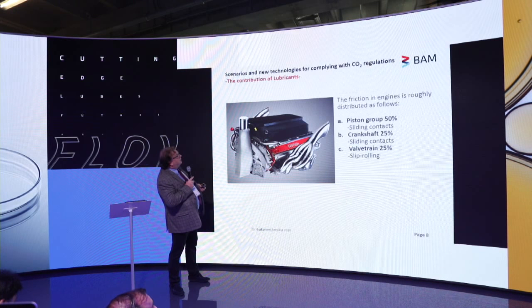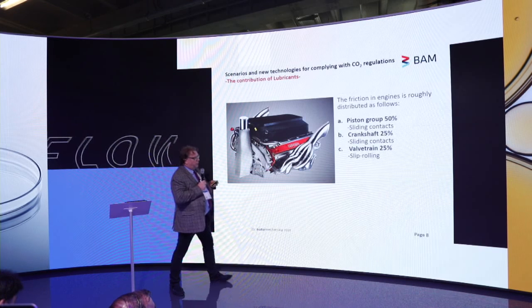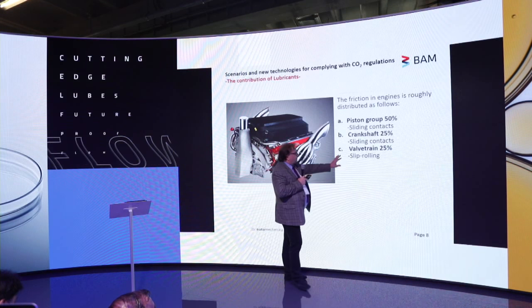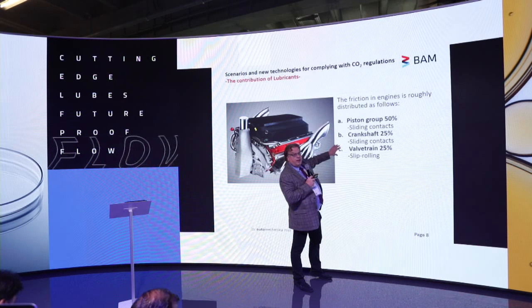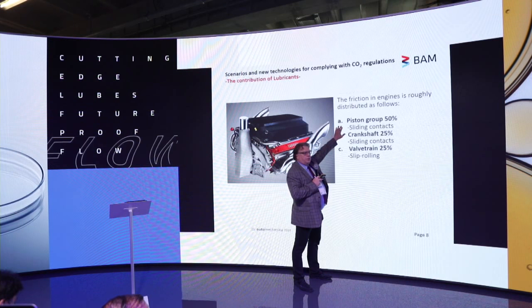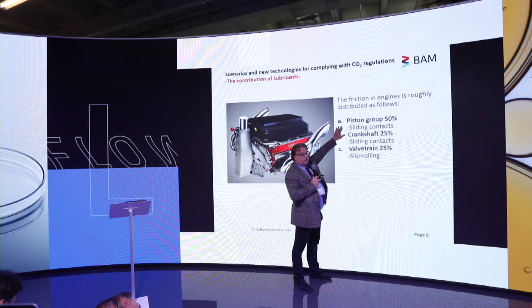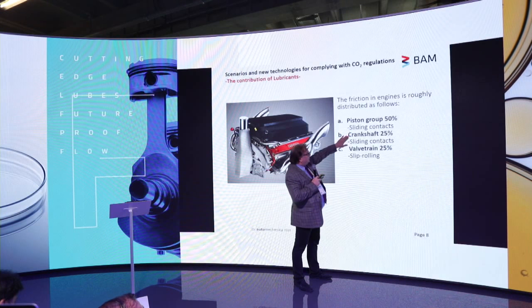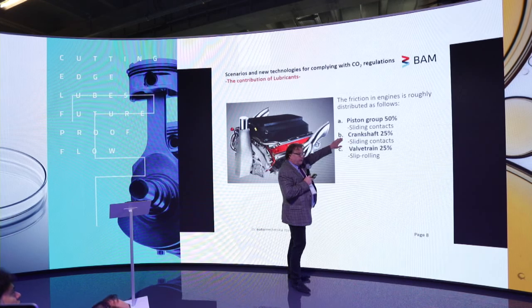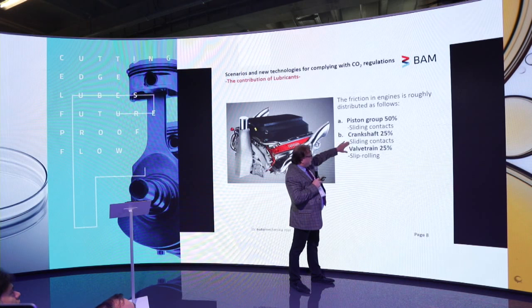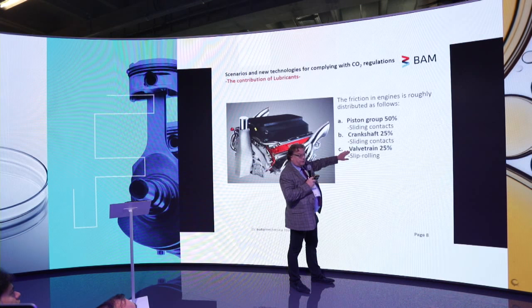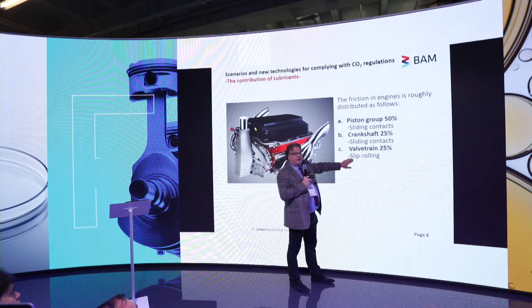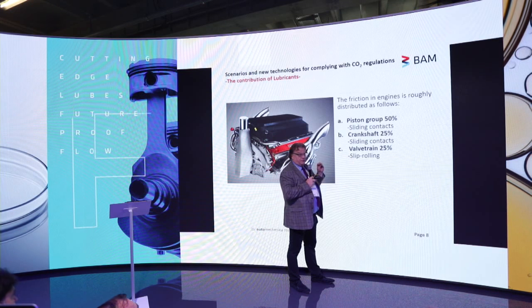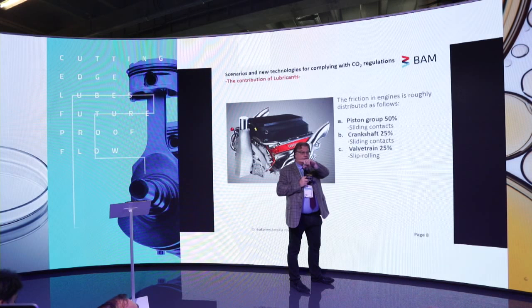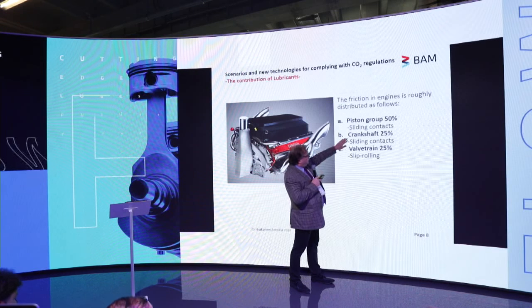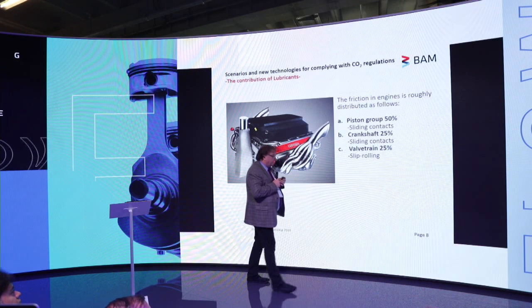So why work on an engine oil? You must separate the three main groups. The piston group roughly gives 50% of the friction of an engine. You have sliding contacts. Crankshaft, roughly 25% of the engine friction, you have sliding contacts. Valve train, also 25%, but here you have a slip rolling contact with high contact stresses. You can see the difference between sliding and slip rolling contacts.